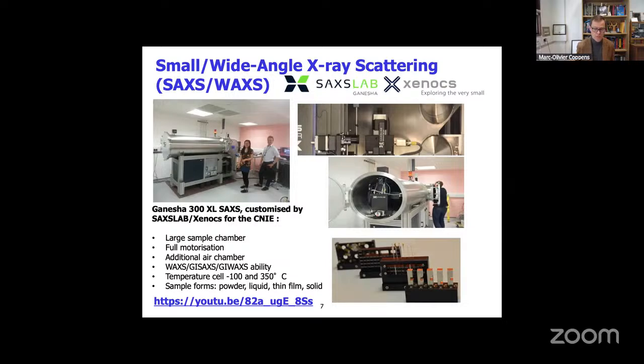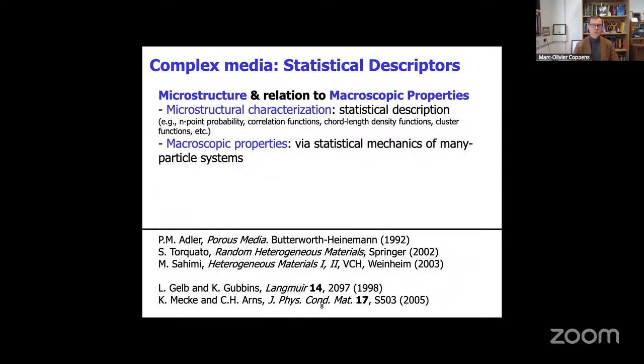Yet another way is to consider that porous media, as I've shown with that example of gamma alumina, are very complex. And so we can use statistical descriptors. And this then is a way of relating the microstructure of the material to its overall macroscopic properties. So on the one hand, you have a microstructural characterization, which you can get via porosimetry, via X-ray scattering, and it can give you information on, say, the overall porosity, correlation functions, chord length density functions, cluster functions, and so forth, and then relate these to macroscopic properties.